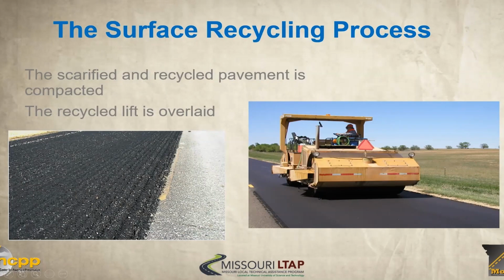So if you look at it here, we're compacting this recycled material for the surface recycling. Now, one thing to note is this is typically, because we're penetrating down about 1 inch, this is typically why we put some sort of other surface treatment on the top, because in essence, this is recycled material, and it might be good if you look at the longevity of the pavement to really look at another overlay or maybe a micro slurry chip seal over the top.